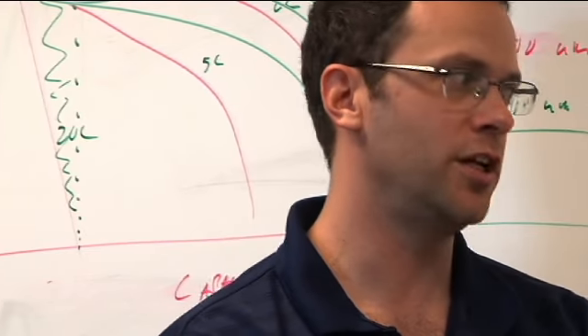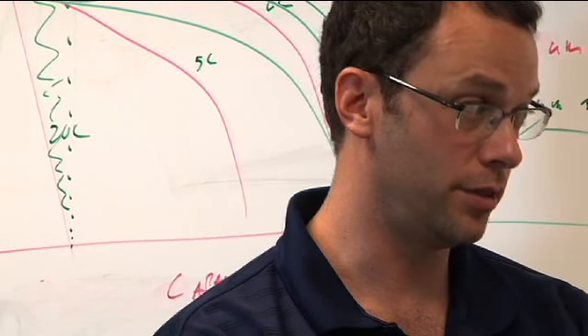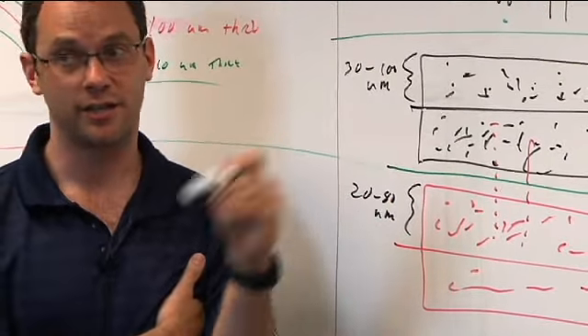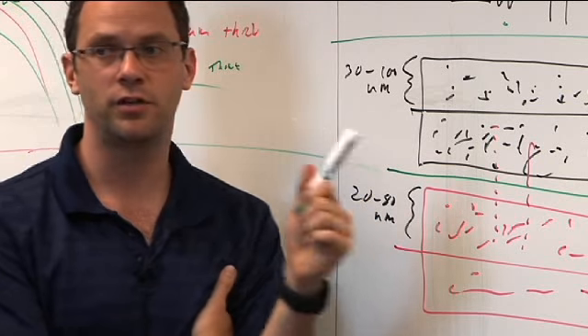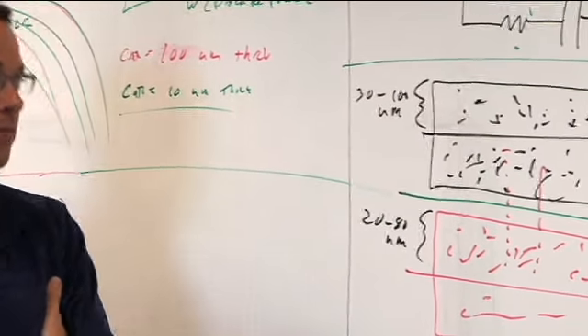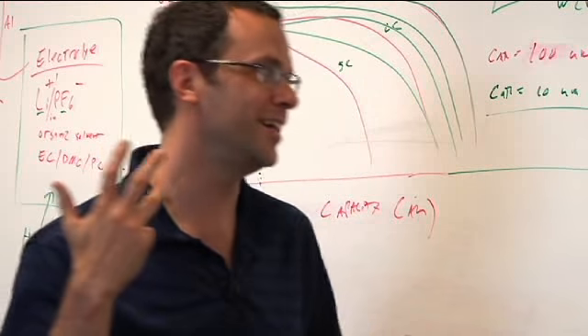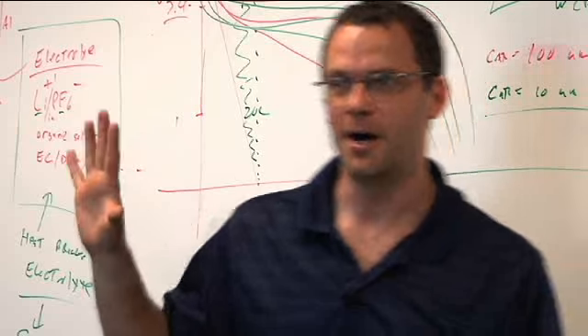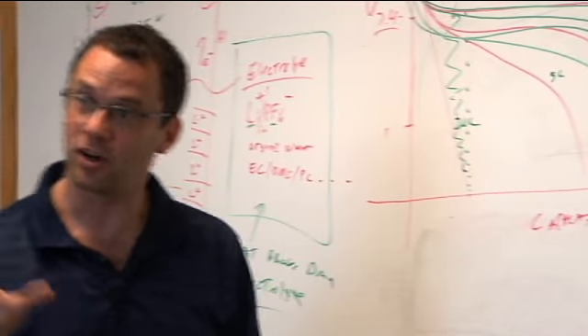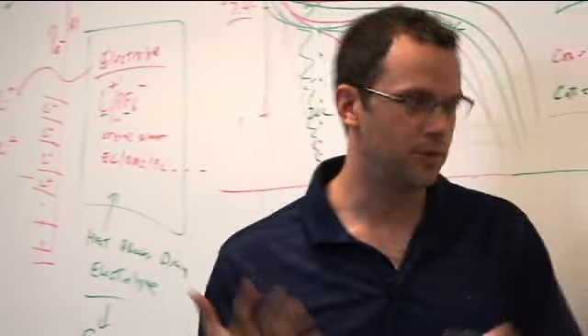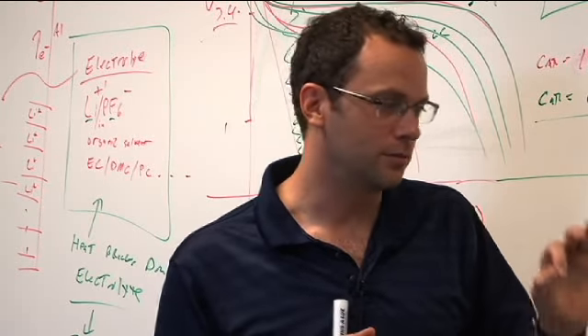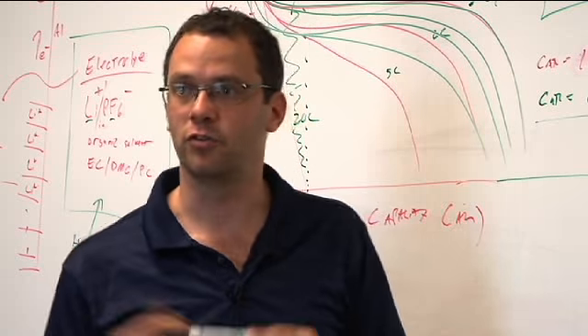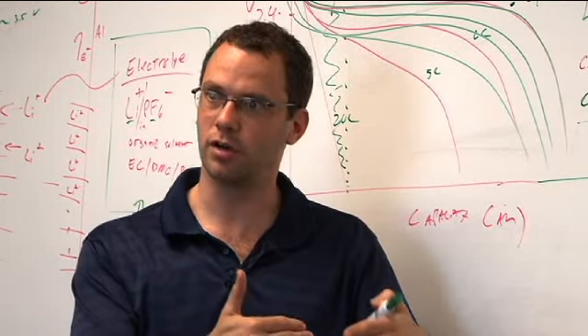And again, it's greatly dependent on, so there's a time constant associated. There's a diffusion time constant associated with the lithium moving through these electrodes, and that time constant depends on the thickness, depends on the porosity, depends on what we call the tortuosity. There's another factor called the rugosity. These are all materials properties: tortuosity, rugosity, porosity, surface area, thickness. There's a lot going on in here that determines that diffusion constant. And of course it's an additive sum. But you end up with some value, and the duration of your pulses is going to be aimed at that diffusion time constant value.